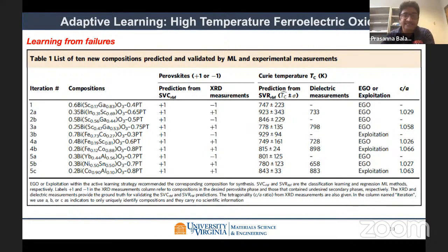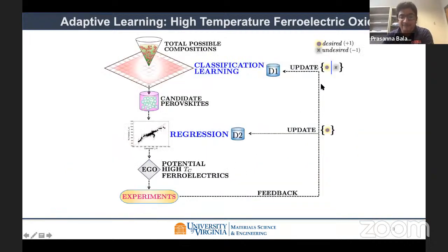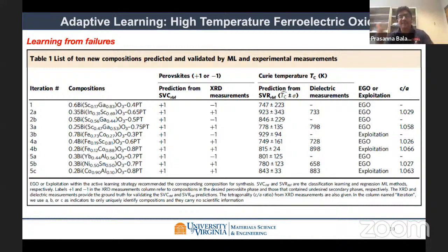Because this is a fairly busy slide. The first iteration recommended the first composition. Hopefully you can see my mouse pointer. The machine learning algorithm predicted this to be a perovskite crystal structure, whereas the X-ray diffraction measurement indicated it had a secondary phase. So this was a failed prediction, because we predicted something that did not work out experimentally. So we fed this failed result into the data set and retrained the classification learning algorithm.